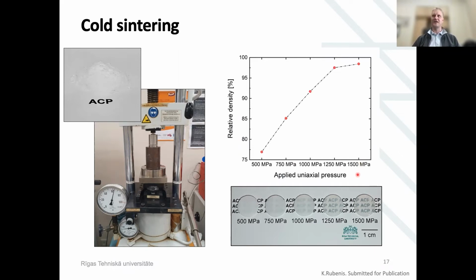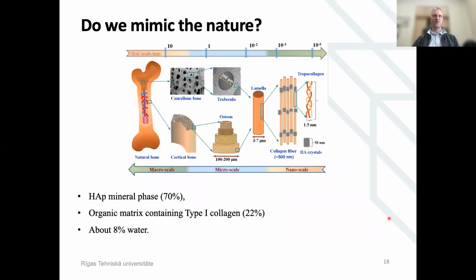So the pressure is really, really high, and achieving these high pressures, we can densify the material very high, and also consolidate, and at the same time we can preserve the nanostructure of the material that is much closer to the bone than conventional sintering. So with this, we were satisfied, but the problem is what we don't see here is the porosity. So at this point, we know how to produce dense materials, but we still have to introduce some porosity in here. So now if we look, do we mimic the nature?